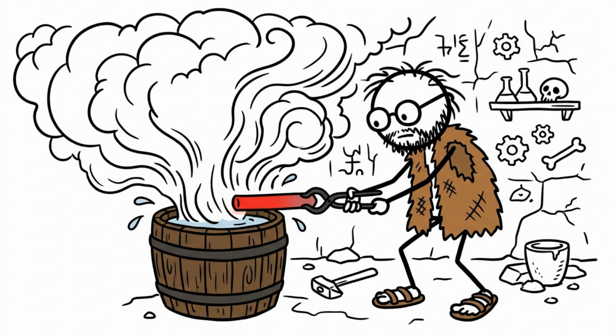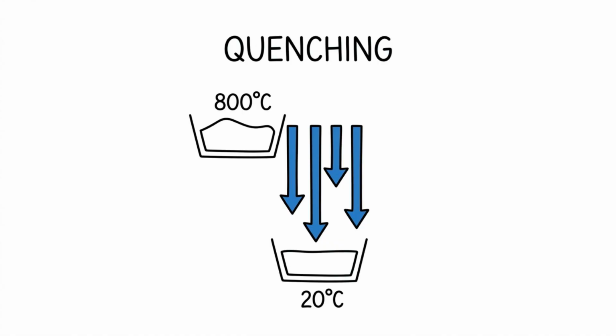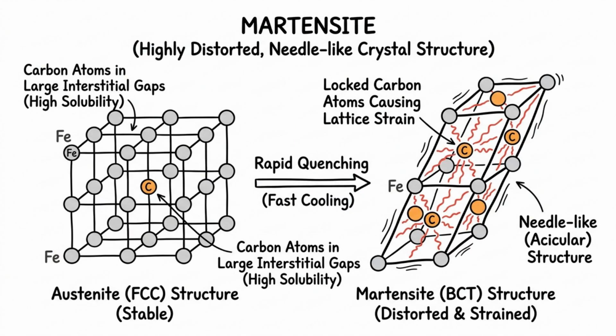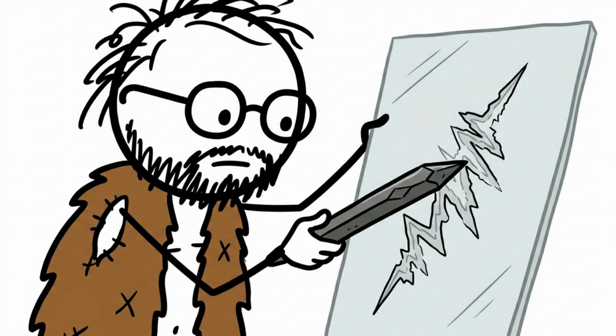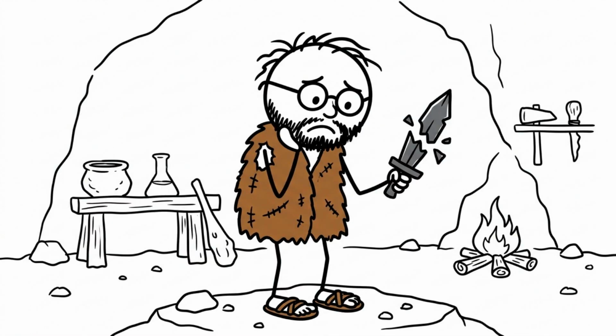You plunge the hot steel into cold water. This is quenching. The rapid cooling traps the carbon. The iron atoms cannot return to their normal shape. They form a distorted, needle-like structure. This structure is martensite. Martensite is extremely hard. It can scratch glass, but it is also very brittle. If you drop it, it will shatter.